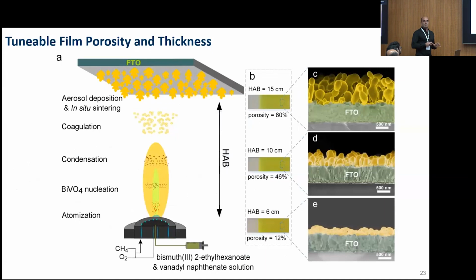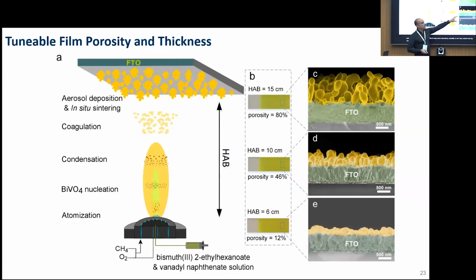Lastly, I wanted to show you one thing about this method too. It enables us to control the porosity of the layer. Now I'll show you this very porous structure. Actually, it's not very robust. But by sintering in situ during deposition, we can go all the way from 80% to 12%, making a very strong layer, and see which ones are the most performing in terms of porosity.